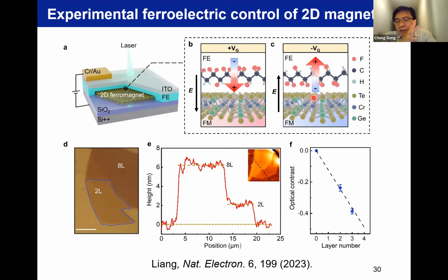As said, a pure electric field, in principle, can cause the effect. I think in 2018 there were at least five good papers published in high-profile journals on electric control of either chromium triiodide or iron germanium telluride or chromium germanium telluride. But in that work, I did not see the focus on coercivity. In chromium triiodide, people observed the switching field, a flipping field at around 5,000 or 6,000 Gauss. You can control it. But here the question is whether you have non-volatile control. That's a very key difference.